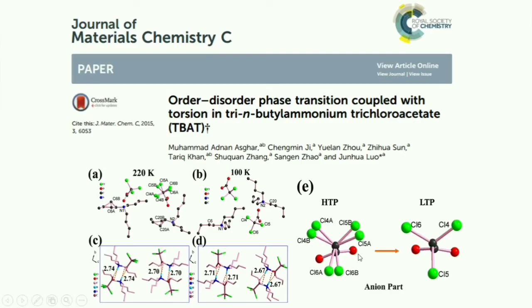So when we collected the crystal data of the same crystal at different temperatures, high temperature and low temperature, we observed that below the phase transition point, which is the low temperature phase, all the atoms are in an ordered state. The red one is the oxygen, the black one is the carbon, and the green one is the chlorine. When it jumps from low temperature phase to high temperature phase, the chlorine atoms are highly disordered and occupy two positions simultaneously. So the single crystal diffractometer shows that this molecule is highly disordered,